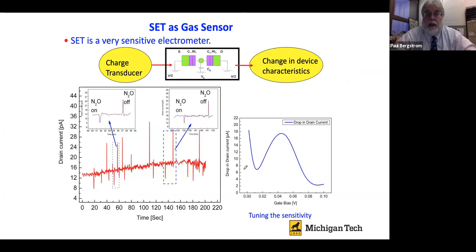We also used this as a gas sensor, where we were looking at permanent gases like nitrous oxide, and we saw that when nitrous oxide would adsorb or physisorb onto the area of the quantum dot, or maybe the area of the gate, the device output would recognize that charge spike as a result of the gas adsorbing and desorbing from the system. So when we would see the nitrous on and the nitrous turned off, we would see these changes in the charge state, and we would then get either a positive or a negative pulse as a result of the gas on versus gas off state. So it was a demonstration again that these devices have characteristics that could be useful in other areas as well. Because these are so sensitive in terms of the charge state, they can measure very, very small numbers of electrons, and that's why they're called a single electron transistor.